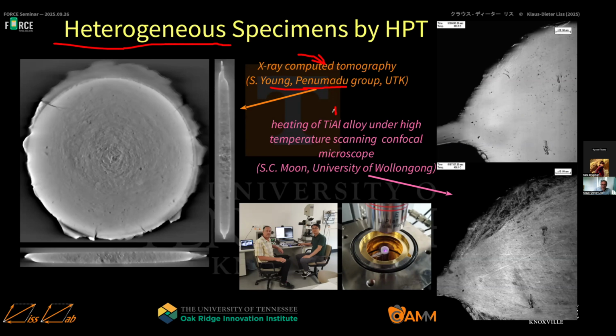Well, here another example is titanium aluminide. So take this part here. You see the edge of the disc in cross section. You cut it and polish it. Then we see this little fringe here, a little fringe to the top, or you see it at the bottom here as well. And this is the edge of the disc where the highest shear strain takes place.